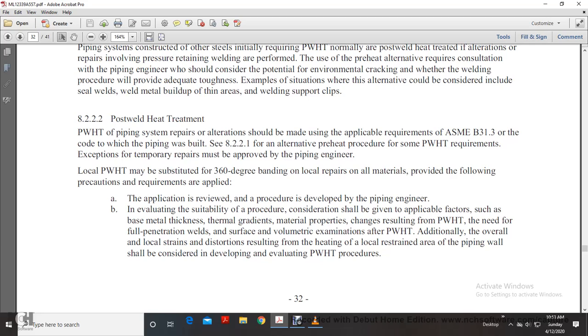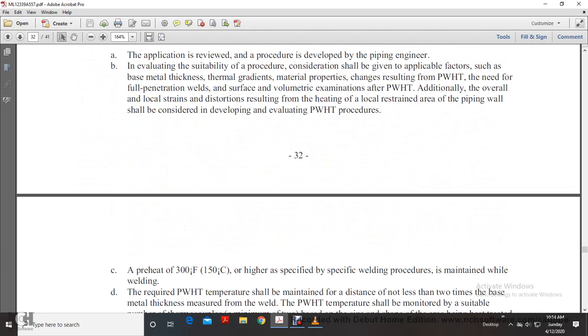Local post-weld heat treatment may be substituted for 360 degree banding in local repairs on all materials, provided the following precautionary requirements are applied. The application should be reviewed and a procedure developed with the piping engineer. Factors to consider include the base metal thickness, thickness gradients, material properties, changes resulting from post-weld heat treatment, the need for full penetration welds with surface examination, and the overall local strain and distortion resulting from heating and localized restraint of the piping wall when developing the post-weld heat treatment procedures.